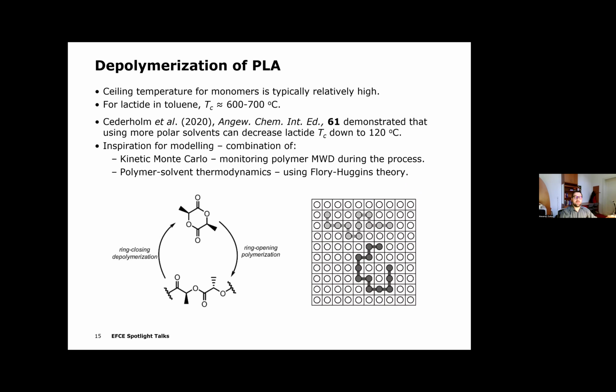But for most of the monomers, the ceiling temperature is typically relatively high. So for instance, for lactide in toluene, the ceiling temperature is 600 or more than 600 degrees Celsius. So in order to depolymerize, we would have to heat up the sample very, very much, which is not really efficient. But in this paper by Cederholm and co-workers 4 years ago, they demonstrated that if they use different solvents than traditional toluene for lactide, they can actually decrease the ceiling temperature down to 120 degrees Celsius.